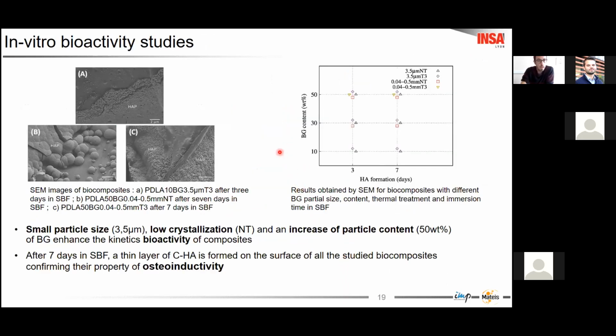An in vitro study allows us to observe the possible bioactivity of our composites. At 50% filler, we observe that the smallest particle size, without any heat treatment, develops a hydroxyapatite layer on the surface of this biocomposite faster than composites with low bioglass content and with particles that have more crystallinity.